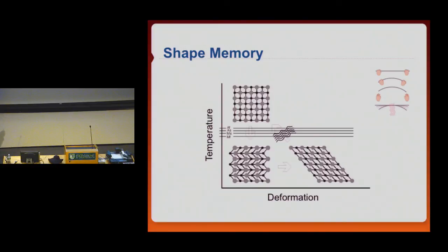So if you cool this particular structure down to below this transformation temperature, it transforms into a monoclinic structure, and this is characterized by twins. The metallurgists in this room know what twins are. They are a special arrangement of atoms. And if you notice, the transformation from here to there does not change the location of the atoms. So this is a diffusionless transformation. At temperatures down here, this one is the stable phase.